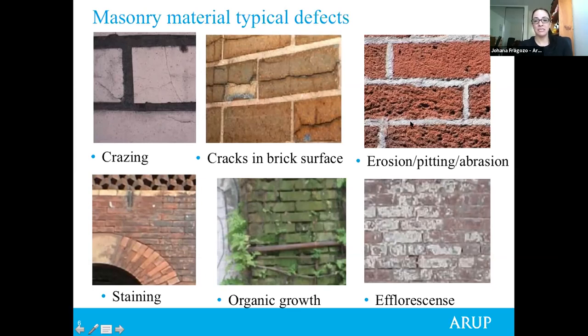Then we have erosion and pitting abrasion. What to look for? We should look for extremely small cavities in the surface of the brick and some minuscule disintegration of the surface. The probable cause could be poor quality of the brick, or that the surface has been previously cleaned by sandblasting, or there has been some improper cleaning method utilized. Staining is usually a thin layer of deposits, usually caused by external factors such as smoke, or rust from corroding steel elements adjacent to the brick facade. And it's mostly of aesthetic nature. It doesn't have any sort of damaging effect on the brick itself.